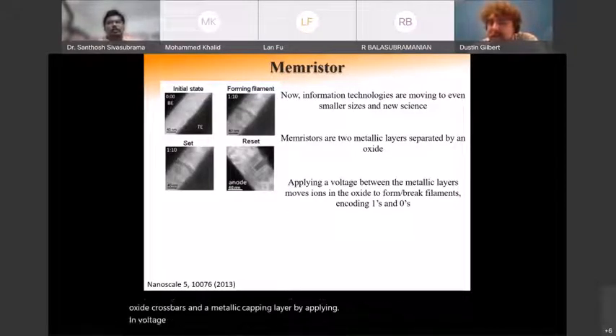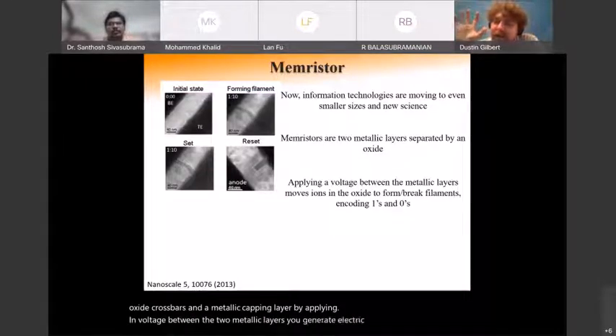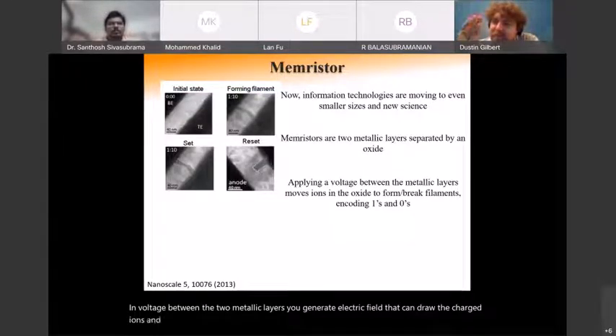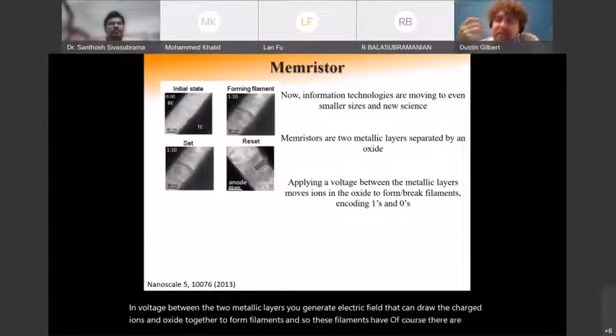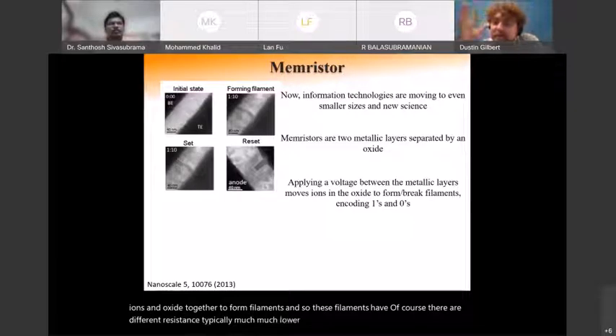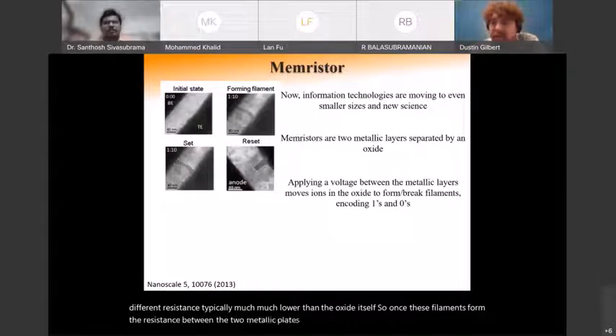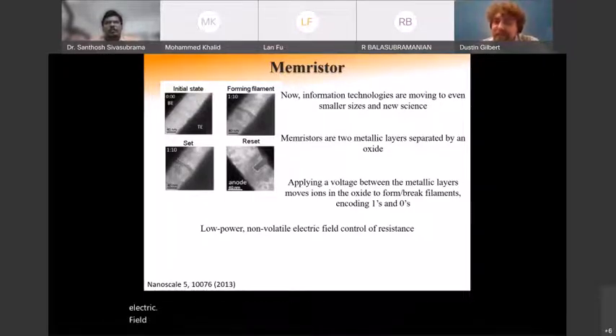By applying a voltage between the 2 metallic layers, you generate an electric field that can draw the charged ions in the oxide together to form filaments. These filaments have, of course, a different resistance, typically much, much lower than the oxide itself. Once these filaments form, the resistance between the 2 metallic plates drops, and so you can record data bits as the formation and destruction of these filaments. It is low power, it's non-volatile, and it's electric field-based control of resistance that you can use then for computations or data storage technologies.